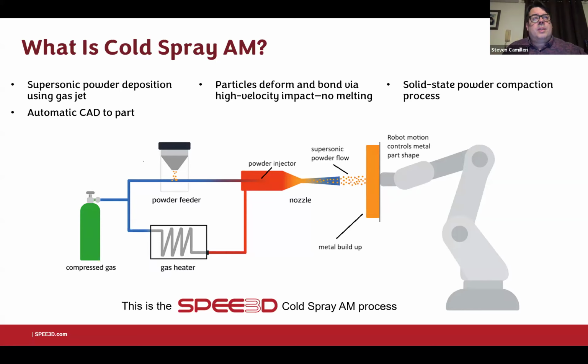So you can't have, for example, throats on your nozzle wearing dramatically and changing the gas consumption, because that'll change the deposition performance. You can't have clogging and buildup in the nozzle, even if it's very gradual. If you're printing for a whole day, for a whole 24-hour period, that'll mess you up, because the material properties will be changing as you go.